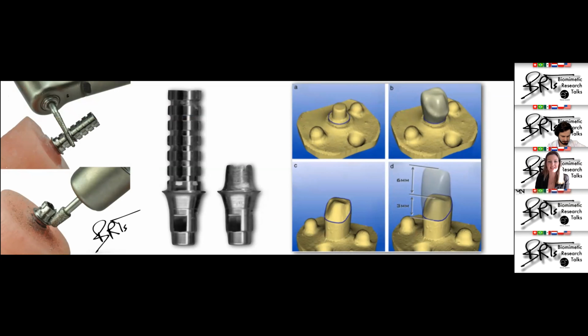And a custom T-base was fabricated. We used Cerec 3 to correlate with the prior study, copying the zirconia abutment, and then we generated a mesostructure that was milled into composite resin blocks, Paradigm MZ100 at the time. Once this mesostructure was bonded on top of this T-base, we could again correlate with Maria's study, using the same format, shape and materials, ceramic and composite resin veneers, to bond on top of this hybrid composite resin metal abutment.